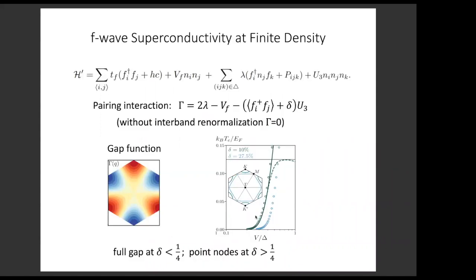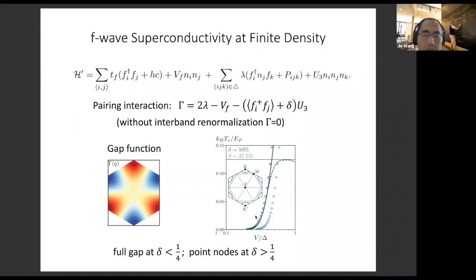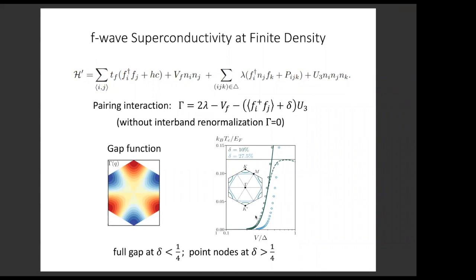Okay, so after finding the pairing for two particles, we can extend this calculation to finite density. And here, let me just start by using mean field theory. Although the original model has only pure repulsion, the effective Hamiltonian from the Schrieffer transformation already has attractive pairing interaction in the F-wave channel. So then we can do a mean field study, and we find the pairing interaction strength is related to these interaction terms in the effective Hamiltonian, 2 lambda minus VF, and the 3-body repulsion we treated in a mean field manner.